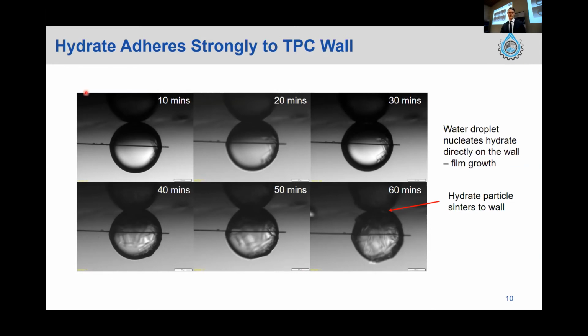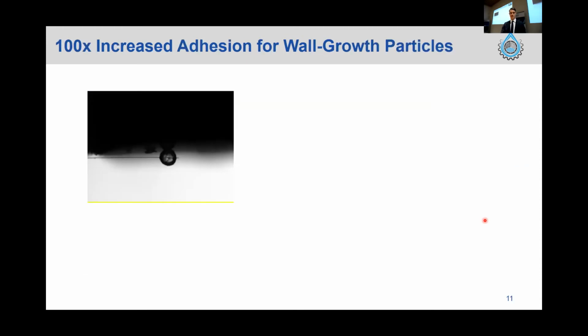And what you can sort of see here is between each picture, you can see the interface expanding. You can actually see this film growth begin to happen. And basically you'll see in the next slide that that film growth really causes the adhesion to increase largely compared to those hydrate particles that were just formed in the bulk fluid. So I'll show you that now.